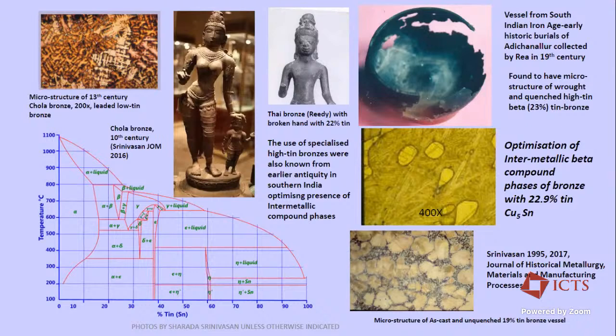And as I said, the reason for not using tin beyond 15% is that as you keep adding tin to bronze, it actually becomes very brittle, and it's not a good material when it gets very brittle. And a prime example of that is here from Thailand, a Buddha image, which contains 22% tin bronze, but this is as cast. And you can see the hand is completely broken off here because this much tin actually causes embrittlement of the bronze. And you can see why that happens here. This is an as-cast bronze, and this is the alpha solid solution phase, as I was talking about. And in the interdendritic spaces, you can see that this phase has formed the alpha plus delta eutectoid, which is what causes the embrittling.